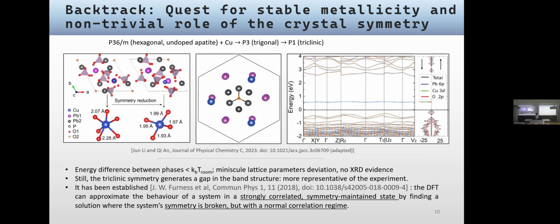Well, beforehand, in terms of DFT, the cuprates were mostly represented as metals, even though they were strongly correlated insulators, as they actually are in experiment. But in this paper, they found that a correct solution, which correctly approximated the experimental situation with the Mott insulating strongly correlated state, can be represented by breaking the crystal symmetry and then finding a solution. So basically, instead of unbroken symmetry and strong correlation, you have broken symmetry and normal correlations, but the resulting band structure and so on looks almost the same in terms of representation of the real picture.